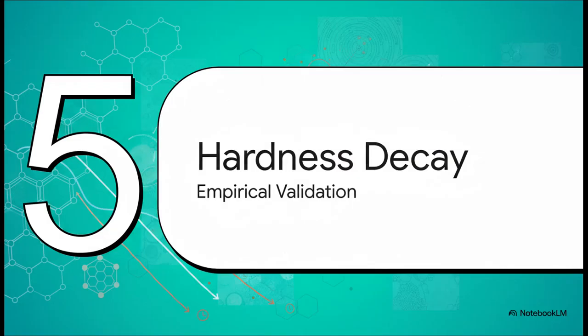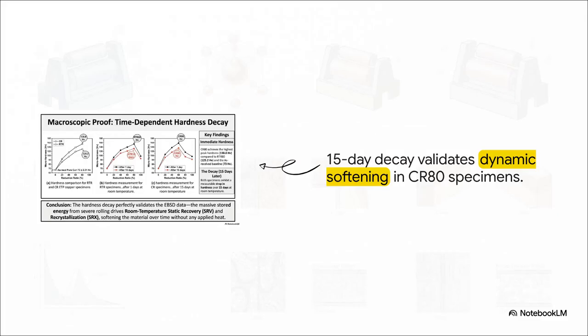Section 5. Time-dependent hardness decay. All right, here is the ultimate proof of that instability we've been talking about. Look at this 15-day micro-hardness decay data. Our cryogenically rolled 80% sample hits this incredible, sky-high initial peak hardness of 138.8 Vickers. But watch the curve. It just relentlessly drops off. This perfectly confirms that the massive stored energy generated by the cryogenic process is driving continuous dynamic softening and recrystallization. And remember, this is happening while the material is literally just sitting there at room temperature.